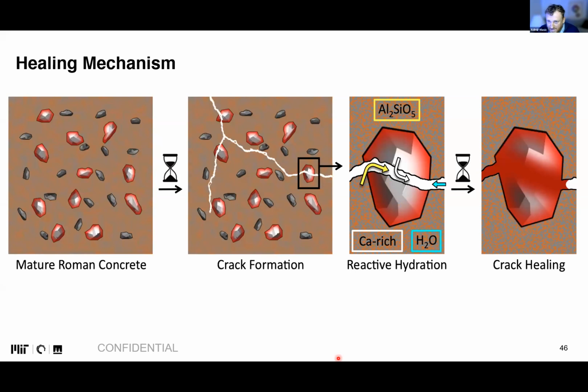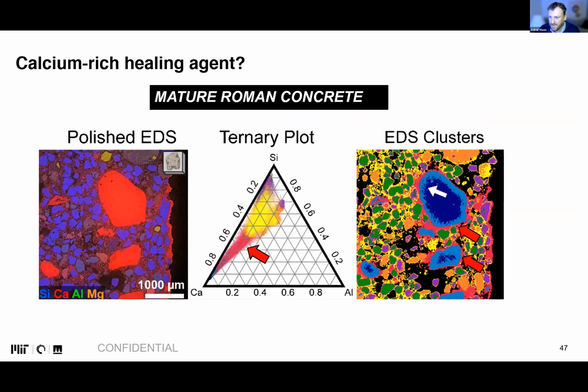But if you now systematically create these inclusions that are potentially a source of calcium for all the reactions that we observe, that means that you are able to produce something that perhaps incorporates reservoirs of agent that eventually will lead to some reactivity over time. And indeed, this image is very beautiful because it shows you the shift in the calcium, silicon, aluminum ternary diagram from very rich in calcium, which are blue. These are our lime clasts, into the red zone. And in the red zone, you see it's enriched with silicon and aluminum. And somehow you see that this goes constantly from each of these little blue aggregates.